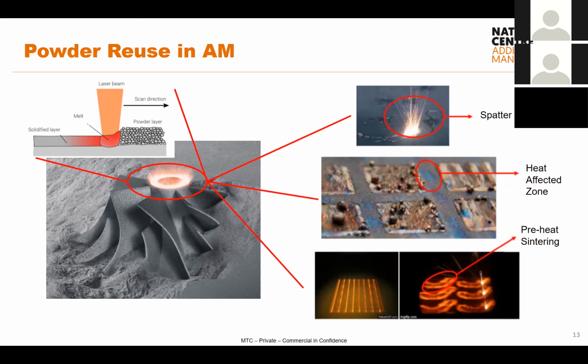Down the system, it's bad news. So you have to sinter. But of course, what that sintering is, it's a soft melting. So you're not fully melting the particles, but you're heating them up sufficiently that they form necks and sinter with adjacent particles. Now, because the sinter area in EBM tends to be quite large relative to the part, coming back to that whole process economics, you've got to be able to reuse that pre-heat sintered powder. So you break it down as part of the recovery process back into its individual powder particles, which then get put back into the machine.